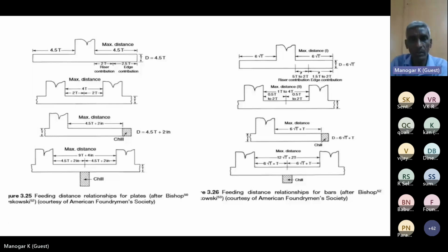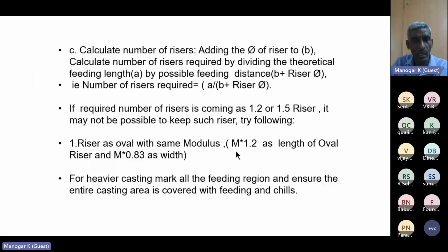Calculate the number of risers, adding the diameter of the riser and the 4T or 5T, with the chill or without chill, whatever is shown, whether you are applying it to a plate or bar, and find out the feeding distance for a particular riser on the section thickness. So the number of risers is found by dividing the feeding length by the feeding distance.